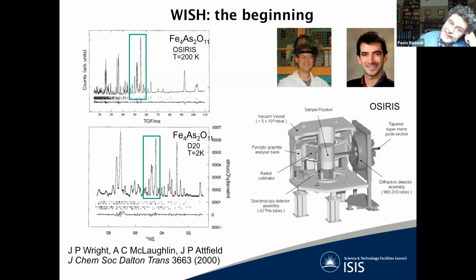And in particular, these data were collected by Paul Attfield and collaborators on a rather complicated structure. They presented in their paper, quoted here, 2 data sets, one collected on D20, which I flipped around so that it looks like time of flight. Of course, it's 2 theta mode, and the other one on OSIRIS here on the top. Now, quite apart from the fact that the D20 data is low temperature, so there are magnetic peaks, you could quite easily tell the difference in resolution of these 2 instruments.